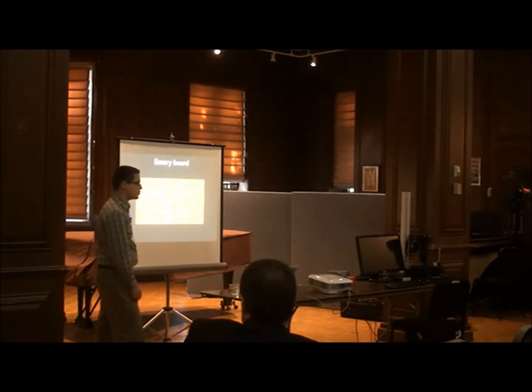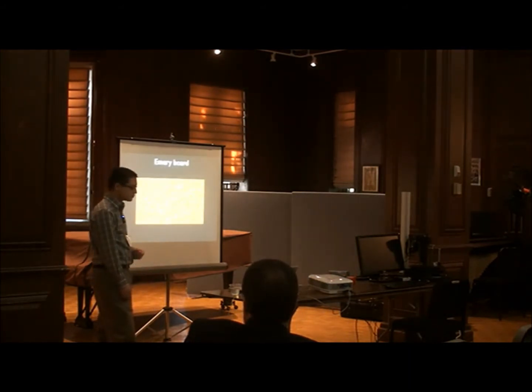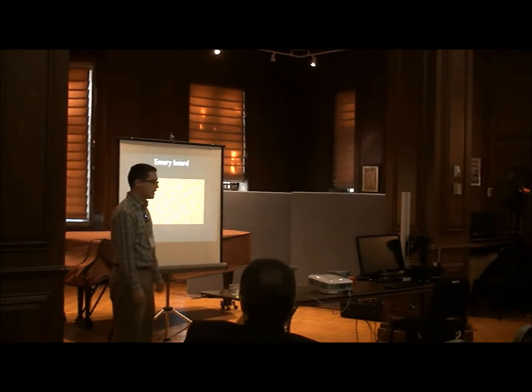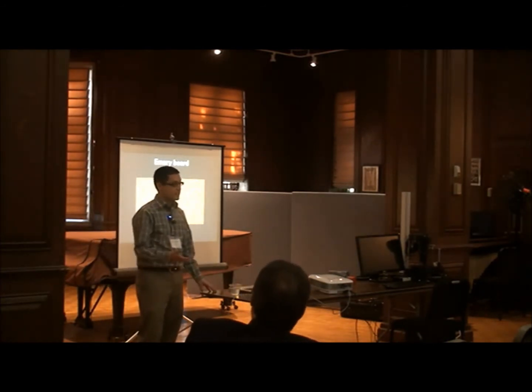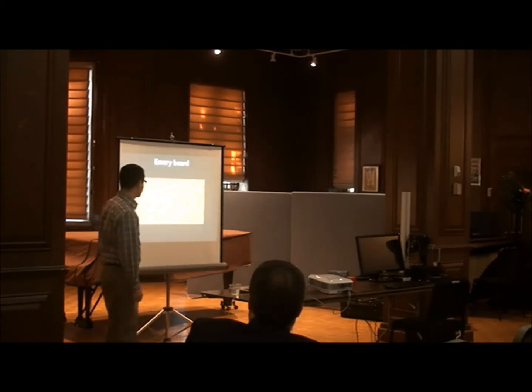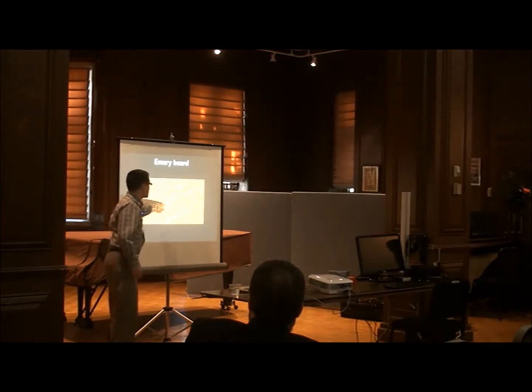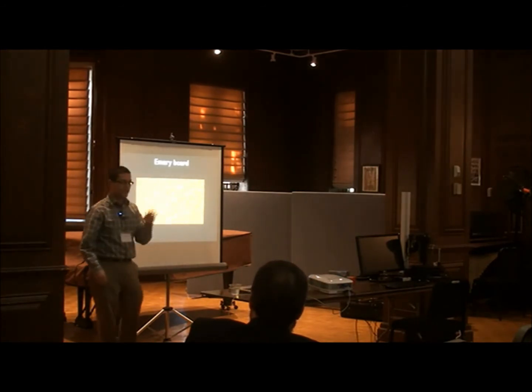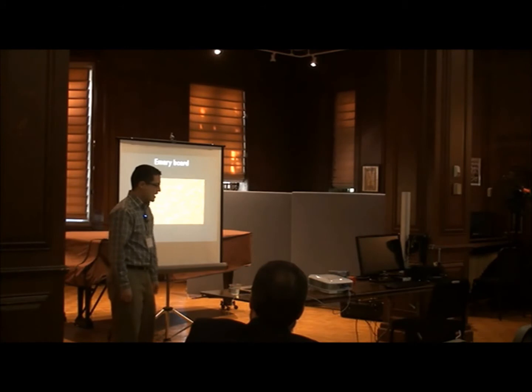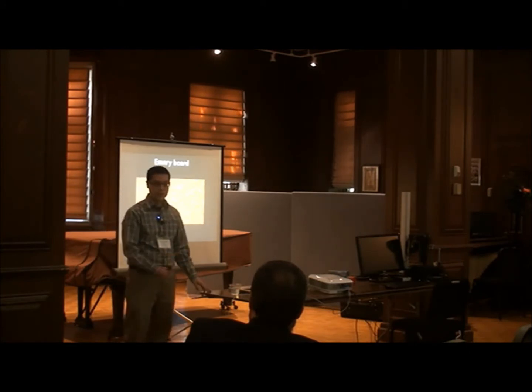If you were to look at this emery board under a microscope, this is what you'd see at fairly low magnification. And I argue that you in fact can't see the surface because the surface is primarily transparent crystals, and the light is propagating into the crystals, reflecting off some spots at angles, creating specular highlights in the image. And there's a lot of complex optical phenomena going on here.